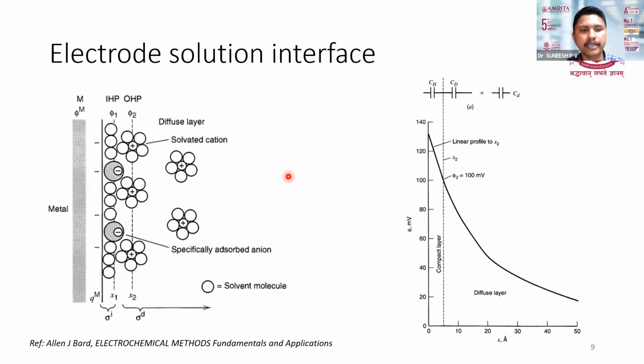So when an electrode material is dipped in an ionic solution, the ions will move towards the electrode, and when we look very near to the electrode, the ionic density will be entirely different from the bulk of the solution. That phenomenon is known as electrochemical double layer formation, where on the electrode surface there would be a certain amount of negative charge, and on the solution side the adsorbed ions will create a layer of positive charge, and a potential difference will be there between these two layers. You can visualize that as a capacitor, because there is a layer of charge on the solution side and a layer of charge on the electrode side.